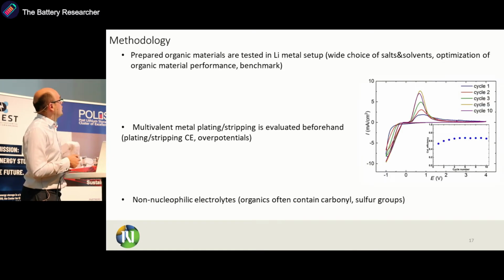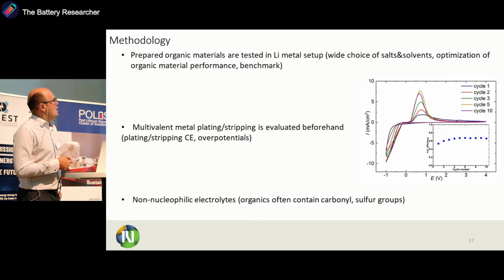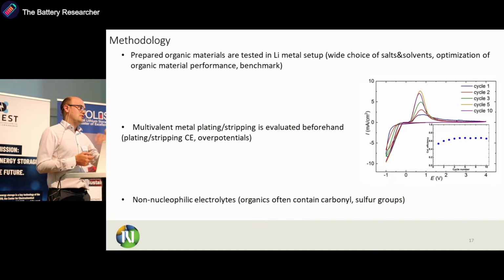Typically, all the organic materials that we synthesize, we test them in lithium metal setup. This allows us quite a wide choice of solvents and salts, and allows us to optimize their capacity, and also later we can get a useful benchmark, because typically we believe that if you cannot achieve a capacity in lithium, you will not achieve it in magnesium. And also if you have higher capacities, let's say in magnesium, most likely you are having side reactions or different